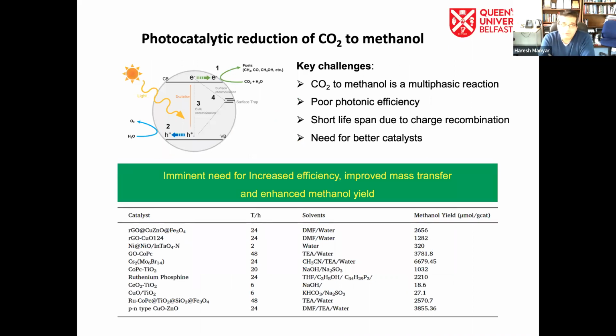Another project that I would like to talk about is photocatalytic reduction of CO2 to methanol. Again, as we can see from here, the traditional approach is using metal oxides like zinc oxides or modified metal oxides. The key challenge of this reaction is that CO2 to methanol is a multiphasic reaction. So you have gas, liquid, solid type of reactors. And you also have photons there now. So you need to enhance the mass transfer. You need to enhance gas-liquid and liquid-solid mass transfer. And you need to bring in the light on the surface, and then you need to combine all of that together. So it's really, really a reaction engineering problem.